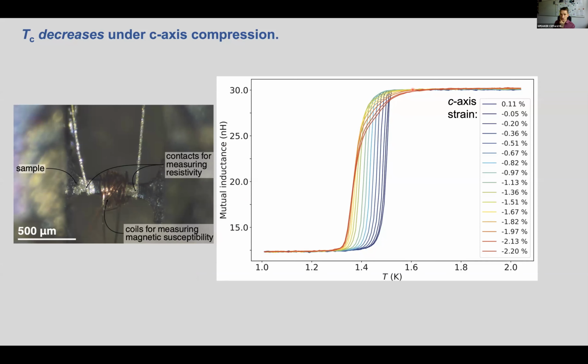And I think this is just an extrinsic effect of in-plane strain. So we're compressing the sample along the c-axis by 2%, and we get this decrease in TC of about 0.1 Kelvin. Now, with an in-plane strain of 0.1 to 0.2%, we increase TC by more than this. So in other words, we have to apply the strain with quite high precision, so we get this 2% c-axis compression without a 0.1 or 0.2% in-plane strain. And I think you're seeing the sort of limits of the precision that we reached on that.